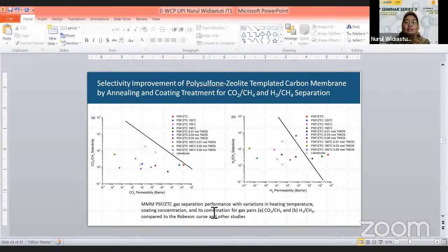As we saw in this figure, the gas separation performance of the polysulfone and ZTC mixed matrix membranes, with variation in heating temperatures, coating concentration, and their combination, for the gas pairs CO2 and methane, and also hydrogen and methane, compared to the Robeson curve and other studies.